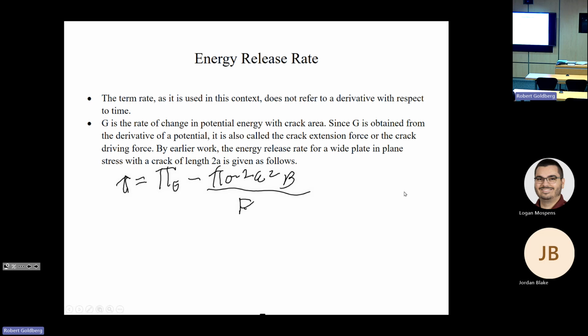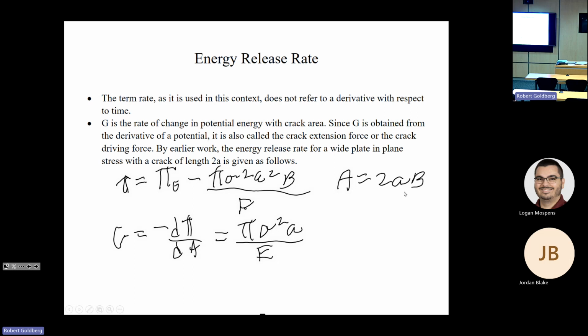So when we take our derivative with respect to the area, we know that the energy release rate is the negative of the derivative of potential energy with respect to area. From this equation, we get that it's equal to pi times the square of the stress multiplied by the crack length divided by the modulus. This is all related to the idea that the area is equal to the whole crack length multiplied by the thickness, and the total area of the crack is 2a, so it's 2 times aB. So when you put in those changes and you differentiate with respect to the area, you get this definition of the energy release rate.